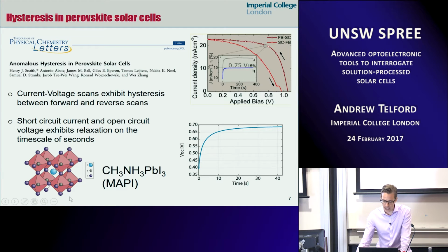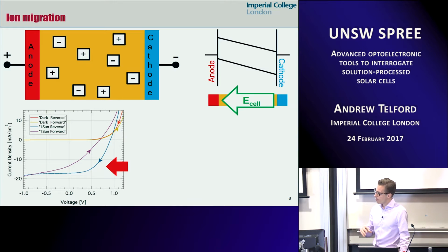And you can see that it has a structure where you have a lot of ions. Okay, lots of ionic stuff. You have iodide, you have lead in the middle of this octahedra, and then you have your methyl ammonium trapped in these voids, in these cages. Okay, so it's not surprising that one of the ways to explain this peculiar electrical behavior, this hysteresis, has been the presence of ions that are able to migrate within the bulk of the material. All right? And it's even less surprising if you consider that this is a solution process material, so it may be non-stoichiometric, so you could have excess ions or a defect of ions, so charged ionic vacancies that can be affected by electric fields.